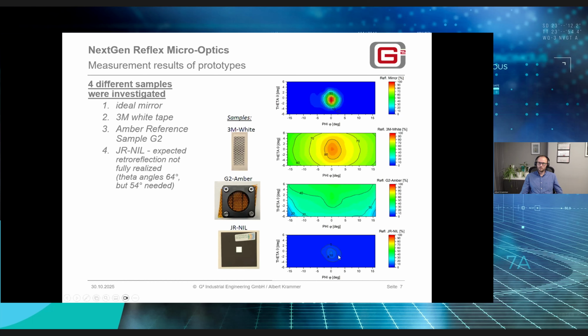So basically the system works, but the negative aspect, and this is caused by the different angles in the prototype, the reflectance is only about 10 to 15% roundabout. So this is definitely not the target. So this was a small deviation, but nothing bad, because a feasibility study also can have negative results.